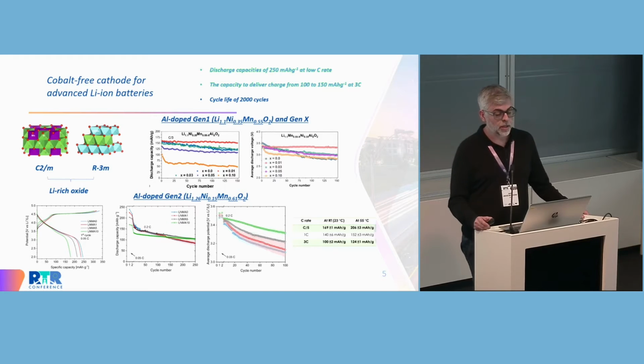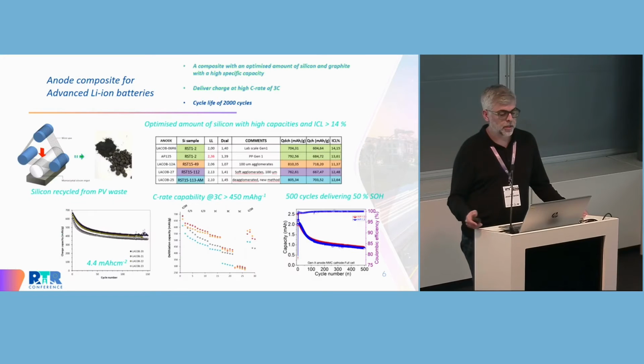Eventually we managed to get some of the achievements that were proposed, which was fast charging up to 3C. We managed to deliver 120 milliampere hours per gram at 55 degrees, at the same time as obtaining high capacities of 250 at low C rates.